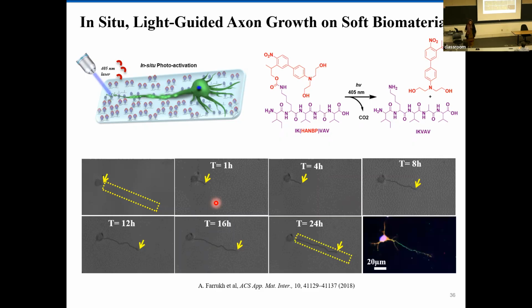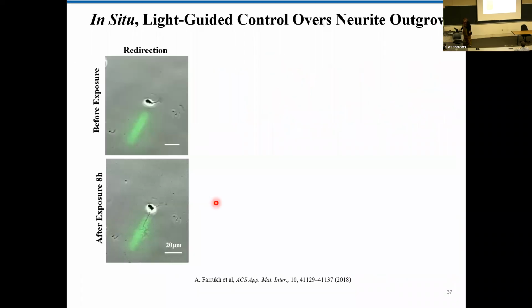And when we did the immunostaining, we can see that this part is green, which means the neurite which we grow is actually axon. So with this system, we can control the growth of axon in situ using our biomaterial. But we can not only control the direction of the axon, we can redirect it. So this neuron is trying to grow in the other direction. If we shine light, it will start growing in the direction of the irradiation.